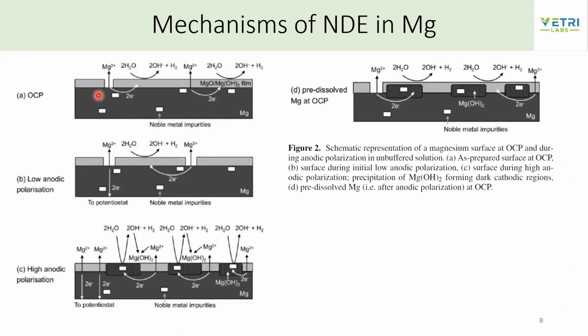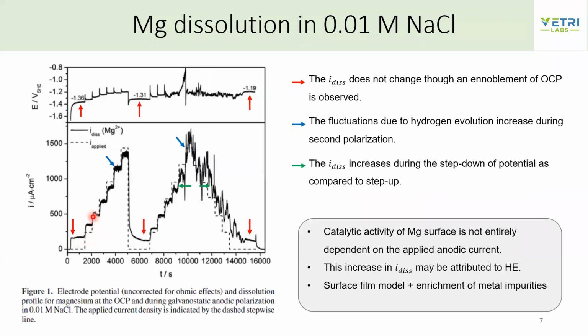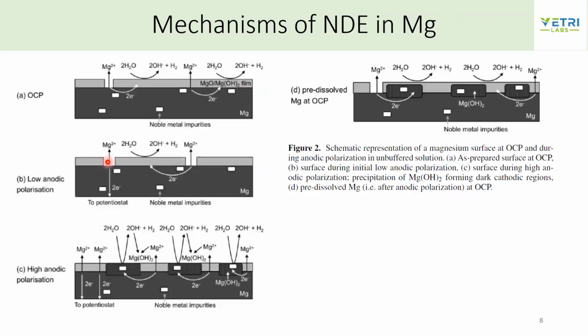So at OCP, magnesium dissolution generates alkaline pH, so they have a magnesium hydroxide film. And then when there is a very low anodic polarization, say the first few steps of this anodic polarization, they have magnesium dissolution, and then they have the slight amount of enrichment happening at the interface.